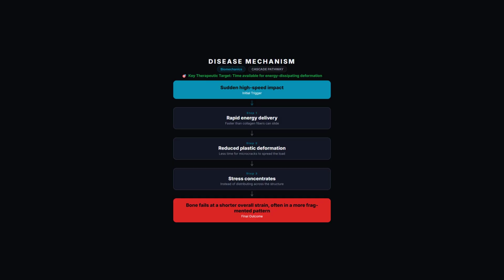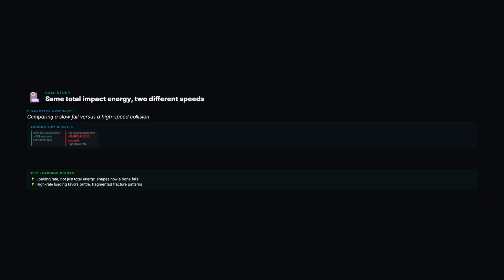Compare two ways of loading the same amount of total energy into a leg bone. In a slow trip and fall, that energy gets delivered over roughly 1/10 of a second, often producing a single clean crack. In a car crash, the same energy can arrive in a few thousandths of a second, and lab studies on cortical bone consistently show this kind of high-rate loading produces more brittle, comminuted, multi-fragment fractures.